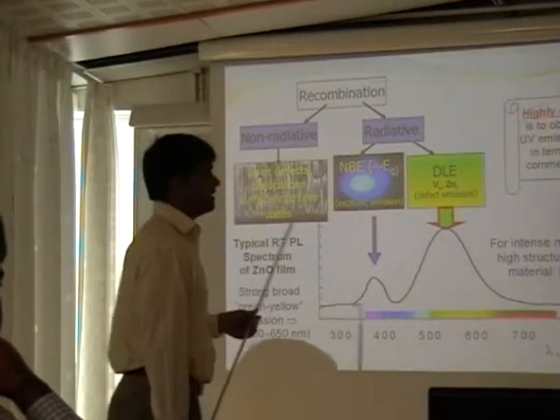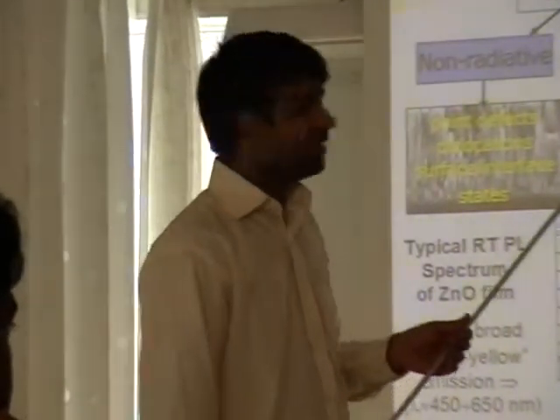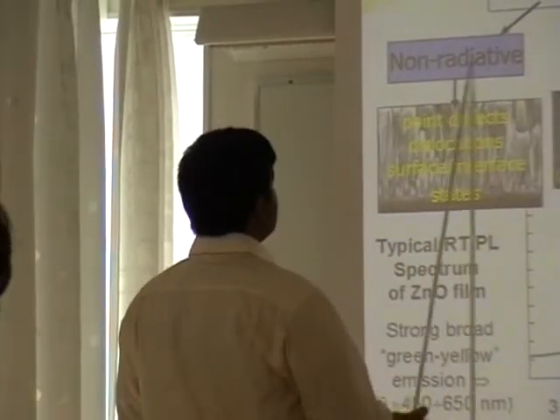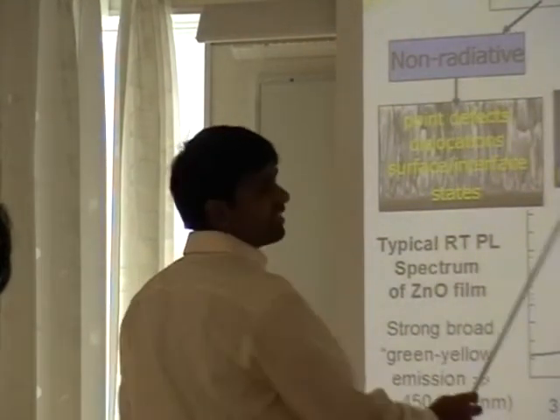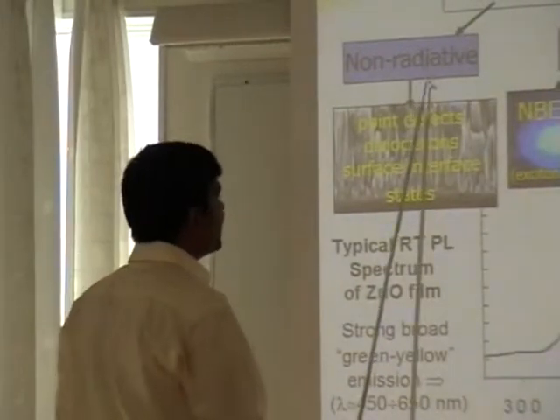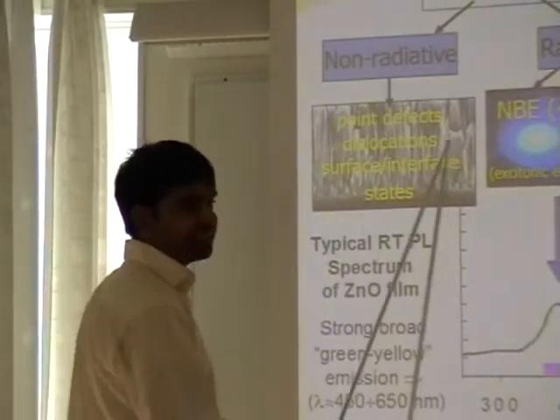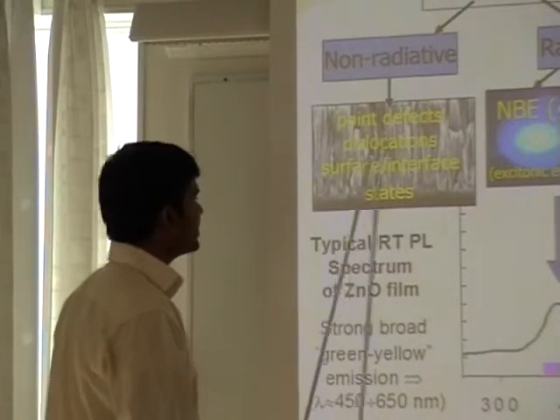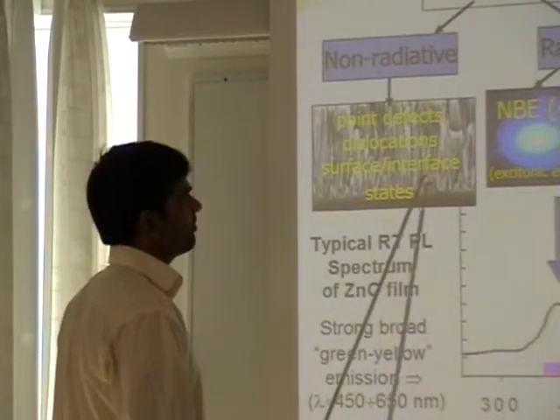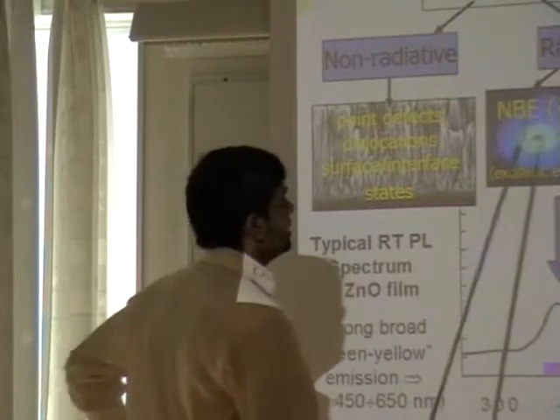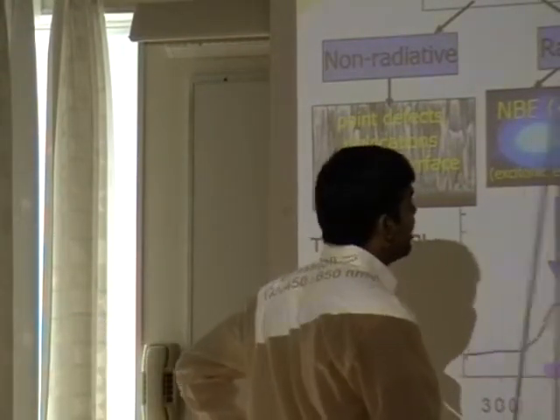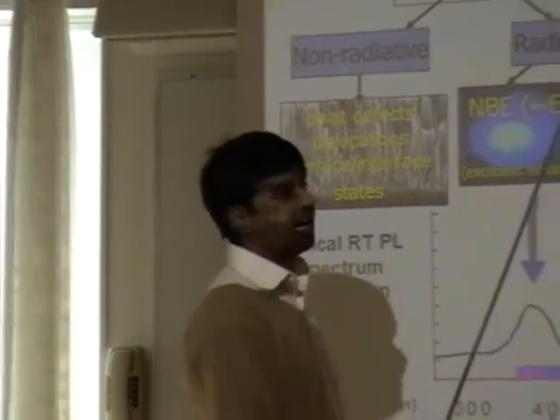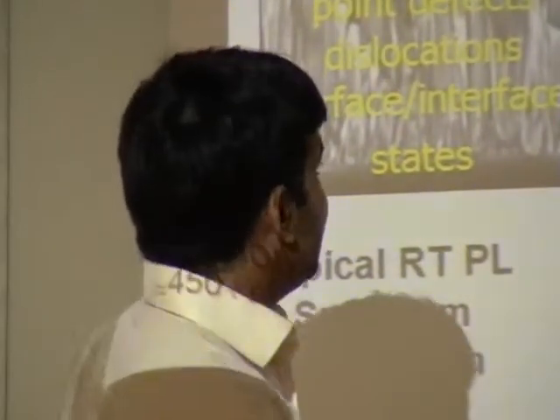Zinc oxide is considered a luminous material. For the recombination, there is non-radiative emission and radiative emission. For non-radiative emission: point defects, dislocations, surface and interface states. While the radiative emission possesses near band edge emission and deep level emission. Near band edge emission is also called ultraviolet emission. In ultraviolet emission, they possess the excitonic emission or exciton.